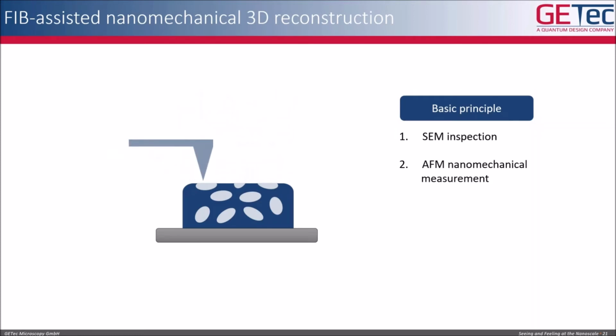Afterwards, we used the AFM to measure not only the topography, but also the mechanical properties, so the elastic modulus of the surface. And then we used the ion beam to slice away part of the polymer sample, and then did this experiment in an iterative way.